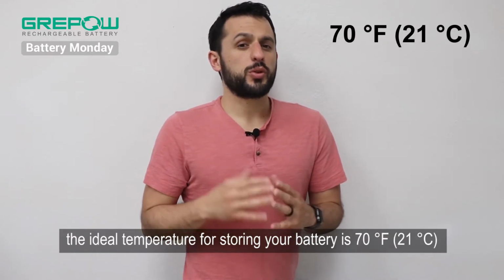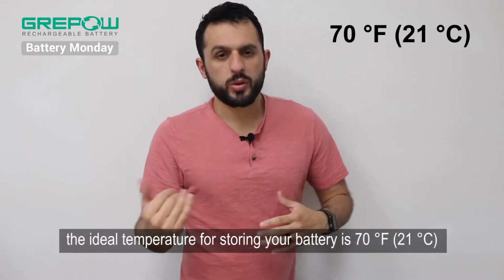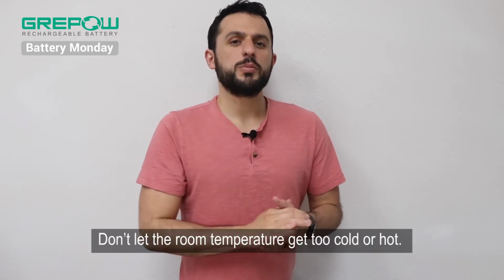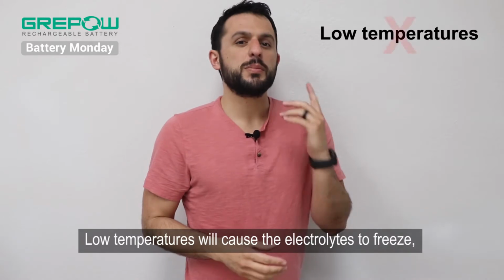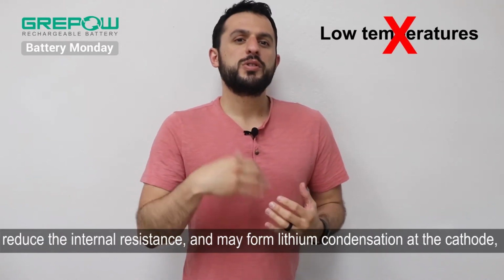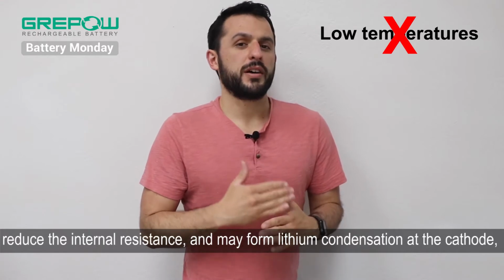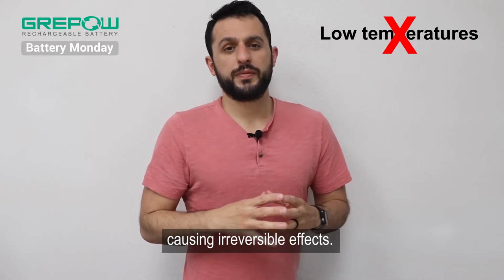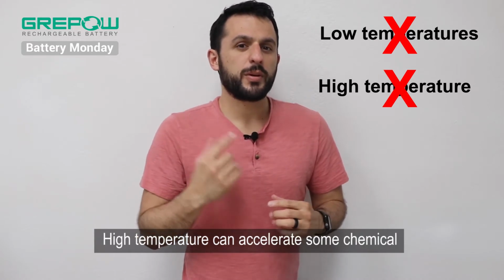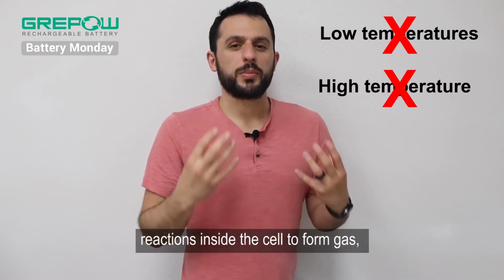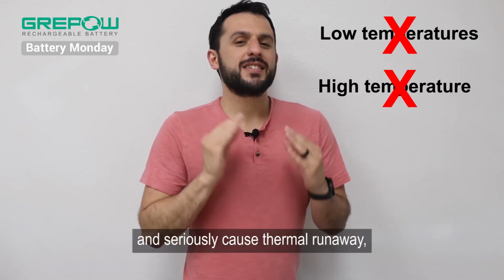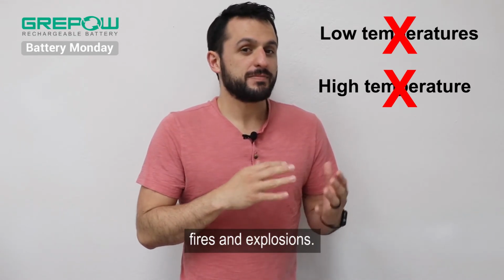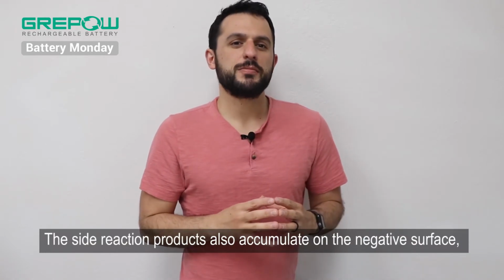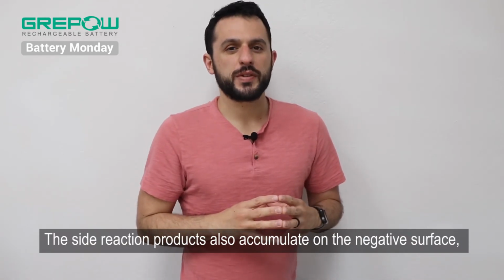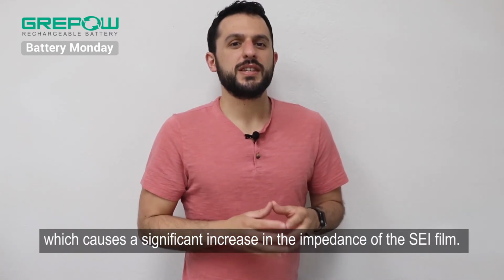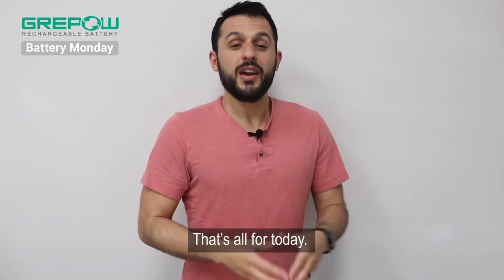The ideal temperature for storing your battery is 70 degrees Fahrenheit or 21 degrees Celsius. Don't let the room temperature get too cold or too hot. Low temperatures will cause the electrolytes to freeze, increase the internal resistance, and may form lithium plating at the anode, causing irreversible effects. And high temperature can accelerate some chemical reactions inside the cell to form gas, shorten the battery life, and seriously cause thermal runaway, fires, and even explosions. The side reaction products also accumulate on a negative surface, which causes a significant increase in the impedance of the SEI film.